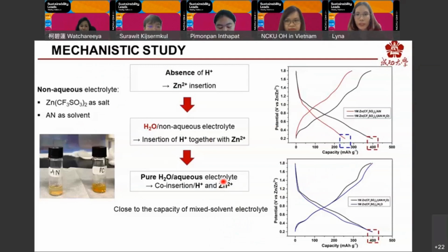To determine the proton insertion, the typical non-aqueous electrolyte was used. These results demonstrate a much lower capacity with the absence of proton. For comparison, we added water into the non-aqueous electrolyte. The capacity from this mixed solvent electrolyte is significantly increased, which may be due to the insertion of proton together with zinc. Interestingly, when pure water was used as the solvent to prepare the aqueous electrolyte, the obtained capacity is close to that of the mixed solvent electrolyte.